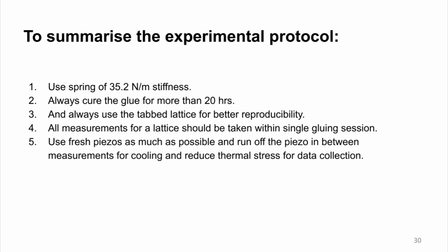To summarize the experimental protocol that I've developed here, I decided to use springs with 35.2 Newton per meter stiffness. I decided to always cure the glue for more than 20 hours. I decided to also take all the measurements within a single gluing session. Although the features are repeatable across different gluing sessions, they are more consistent within a single gluing session. Whenever possible, I decided to take all my measurements within a single gluing session.